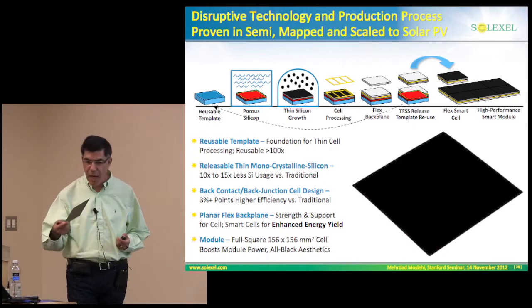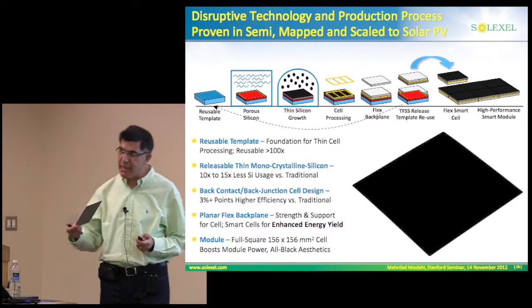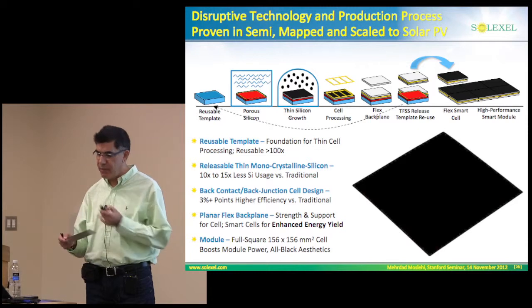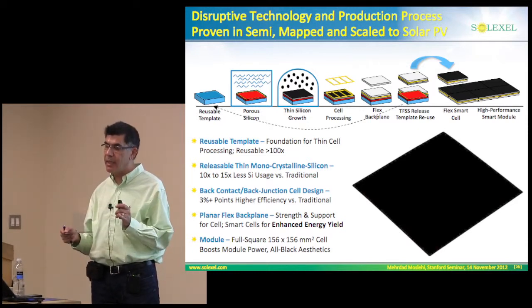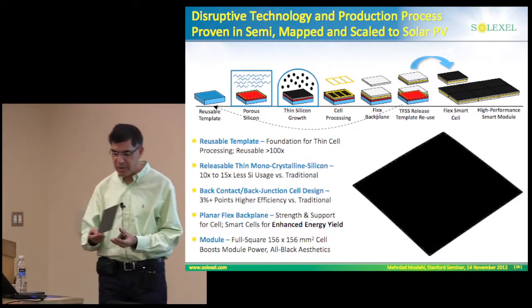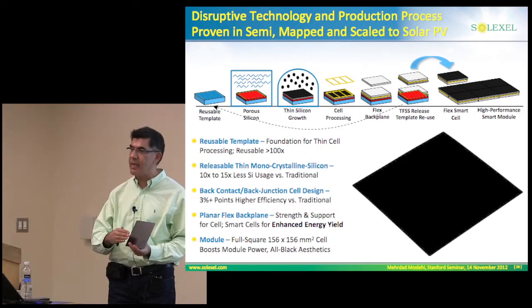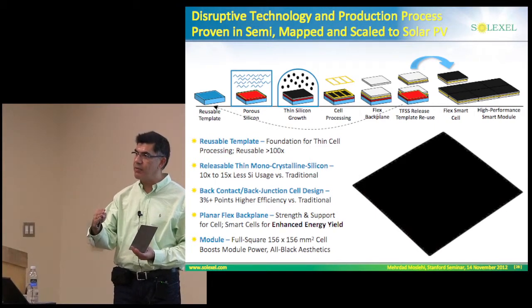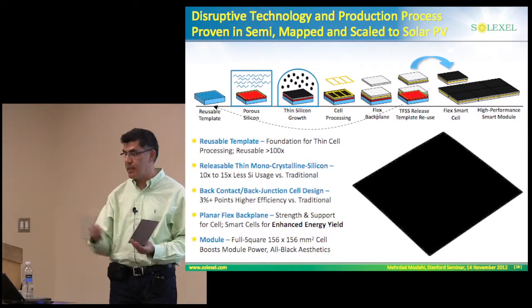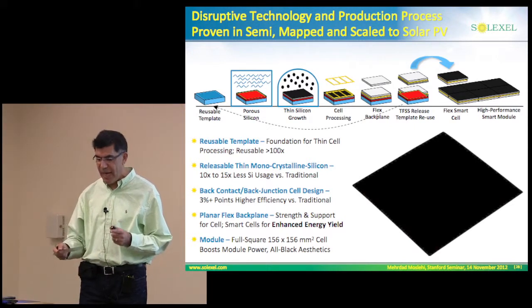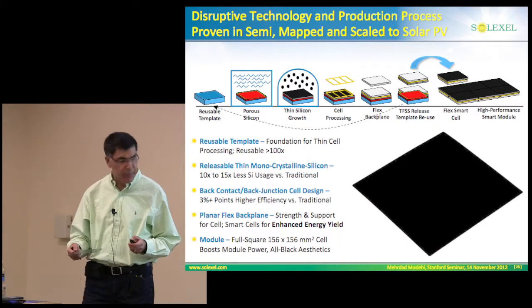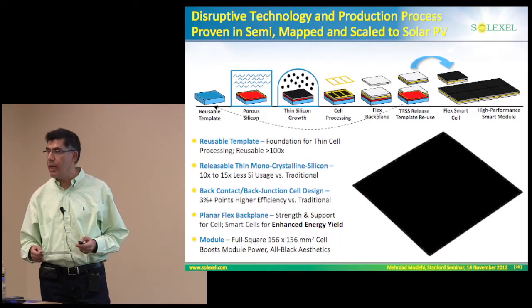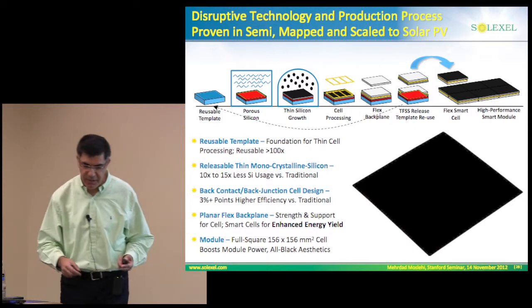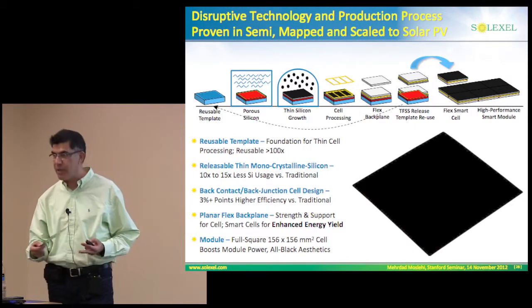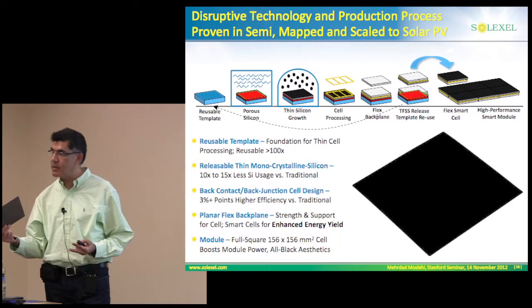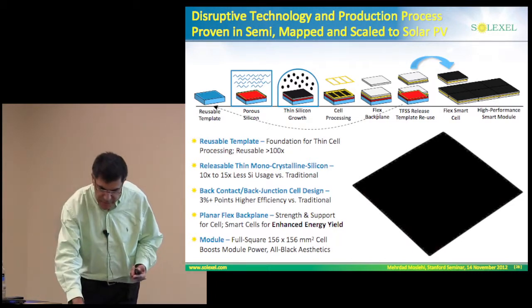And then while the thin silicon is on the template, we finish. Remember, we have a back contact, back junction cell architecture. So our backside of the cell is exposed. We finish all of the backside processing, which is really most of the process steps. And at that stage, we are ready to lift off. So far we have processed the cell on a very robust template, so thin silicon is not compromised in terms of yield.